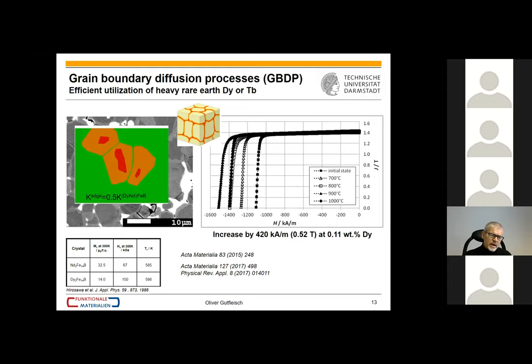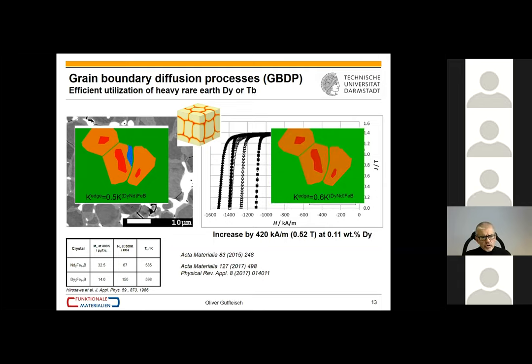Next, we can do micromagnetic modeling, and we see here how nucleation happens as usual at the grain boundary. But here on the computer, you can show easily that if we bring up the anisotropy constant at the grain boundary, then nucleation ultimately will happen and start from the center of the grain. And that, of course, is a much improved scenario.